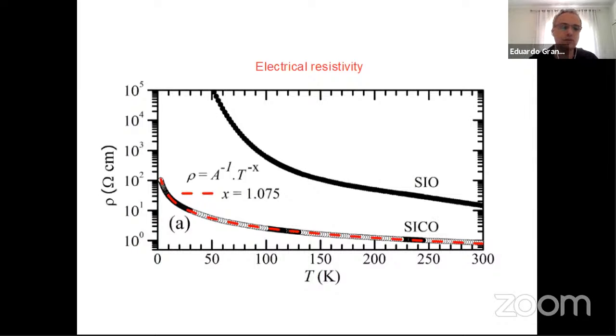But then we go to the electronic properties. We have this resistivity as a function of temperature. For the pure compound, it's pretty much an insulating behavior. If you go to the cobalt doping, you see that the resistivity goes down a lot, but the material doesn't become metallic. It's still non-metallic, but it's not insulating anymore. That's pretty much what we expected, or at least what I tried to convince that we are in the limiting case between one and the other.